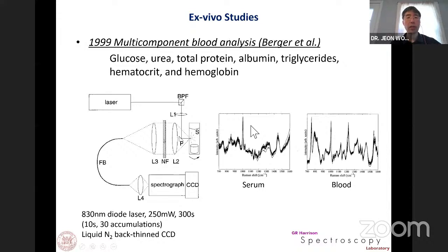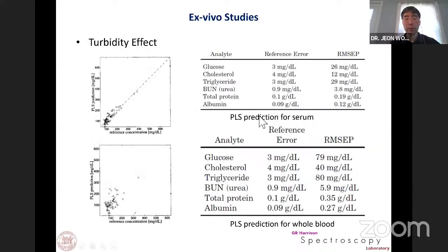Encouraged by this result, we applied the same technique to whole blood analysis. Since the blood itself is very turbid, the first set of experiments was done with whole blood, and the second set was done with blood serum after removing the red blood cells and other floating materials. What we found was that from the serum measurement, we could see the linearity between the reference glucose concentration and the predicted glucose value. We could measure glucose, cholesterol, other lipid components, and albumin with decent accuracy. But when applying the technique to whole blood, because of the turbidity, we could not get good accuracy. That was the issue.